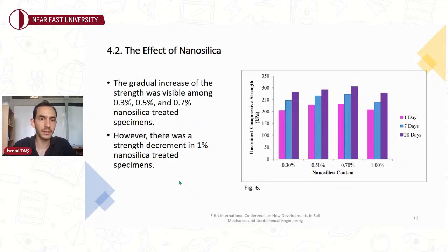The gradual increase of the strength was visible at 0.3, 0.5, and 0.7% nanosilica treated specimens. However, there was a strength decrement in 1% nanosilica treated specimens. The excessive rate of nanosilica had a strength reducing effect rather than contributing to it. Therefore, the optimum nanosilica content was 0.7% in clay specimens.